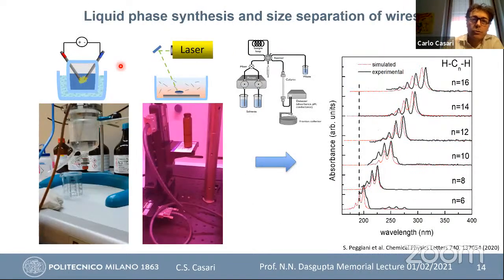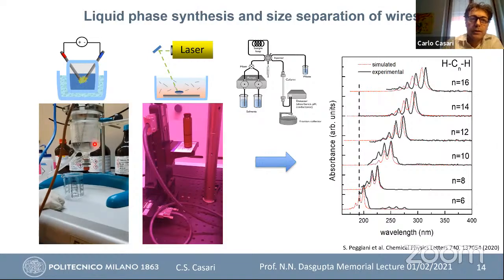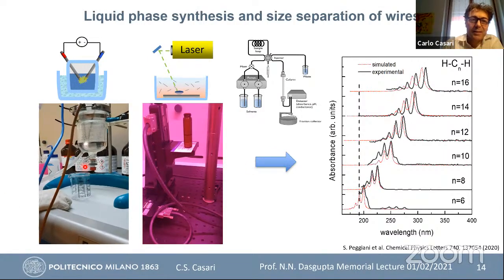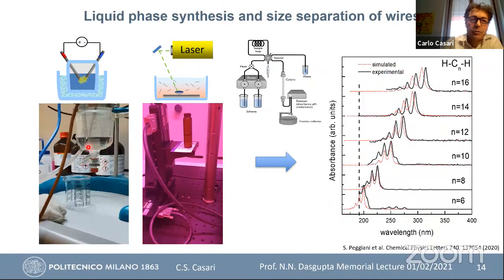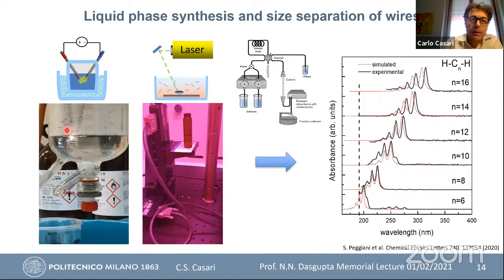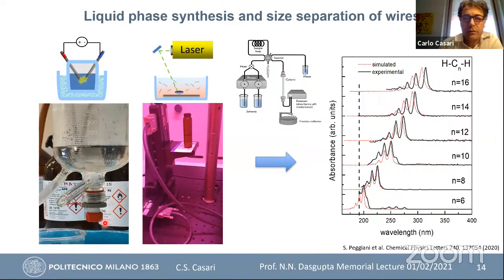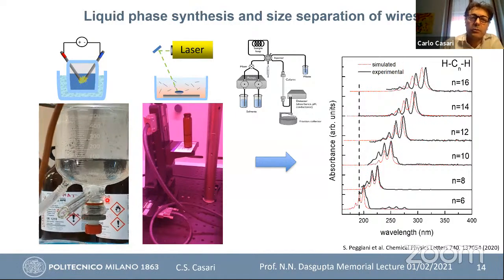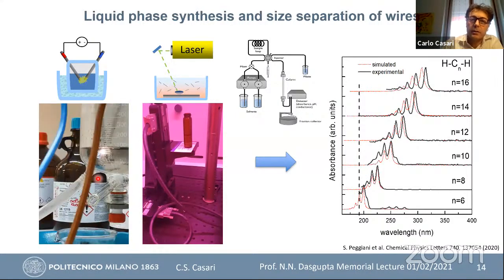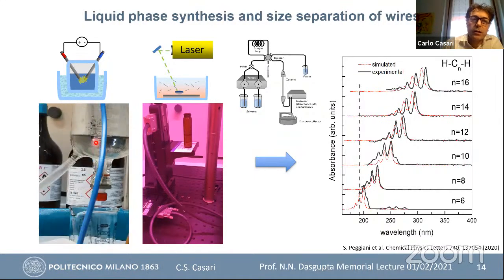I want to show you here what we do. This is the arc discharge in liquid. This is the pulsed laser ablation in liquid. Let me know if it's working. So you can see the arc discharge between these graphite electrodes in a solvent. The solvent plays an important role for forming the terminations and the kind of structures.